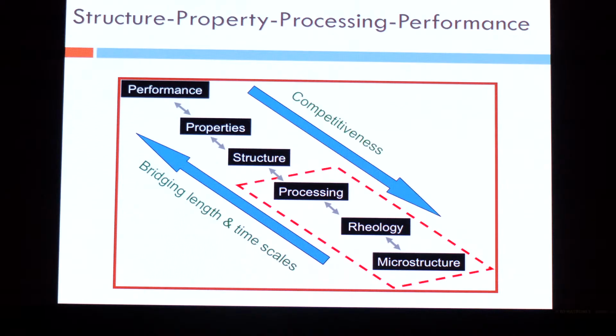And therefore, if one wants to understand really the entire gamut from molecular structure to industrial scale processing, you have to really understand the structure-property-processing relationship. So at the right side, you have the polymer microstructure, which leads to the flow properties that I talked about. These flow properties are important for processing the polymer at industrial scale. Once you make the products, they crystallize and they form these interesting semi-crystalline structures. And it is this structure that gives the properties, the rigidity, the ductility of the polymer. And it is these properties that ultimately, for all of us as consumers, make us think these polymers are great materials. The performance of these polymers is wonderful.